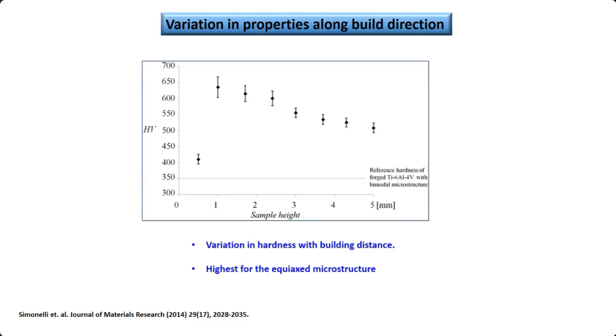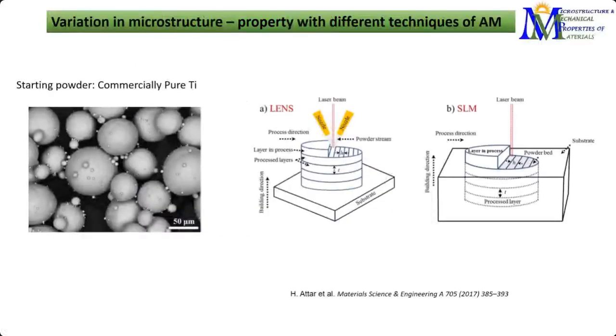Of course, there is variation in the microstructure size and morphology, and that leads to variation in the hardness level also. The highest hardness is noted for the equiaxed structure, so we should always strive for that.